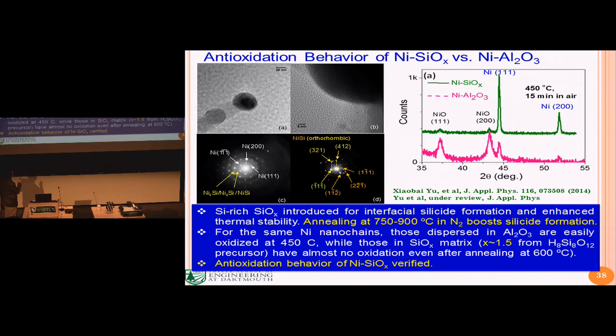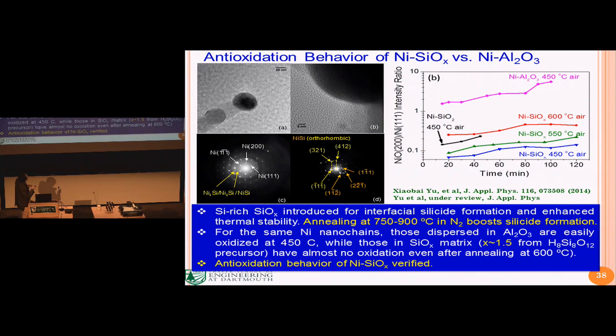And then we anneal the material before its operation in nitrogen at high temperatures. You can see the interfacial silicide formation, and the diffraction patterns of silicide on the interface. Now, if we oxidize this material at the same temperature in the silicon-rich oxide matrix, there's hardly any oxidation at all. We can compare different temperatures. For this nickel silicon-rich oxide system, even at 600 degrees, the degree of oxidation is lower than the nickel aluminum oxide system at 450 degrees. So it's very effective.